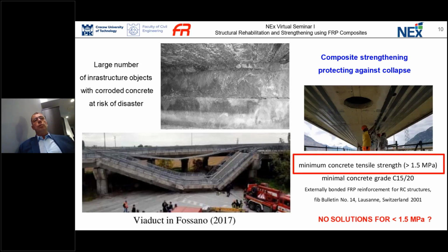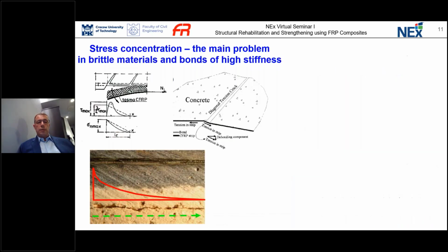Of course, if we would like to improve the strength nowadays, the most popular is composite strengthening, mainly carbon fiber laminates, but there are requirements for using it. As the fib bulletin presented in 2001, the minimum requirement for the concrete is at least 1.5 megapascal of tensile strength measured in pull-off tests. So if the structure is very corroded and the concrete is of poor quality, it typically has the lowest values. And the question is whether there is any solution for such a problem, if we would like to use composite materials.